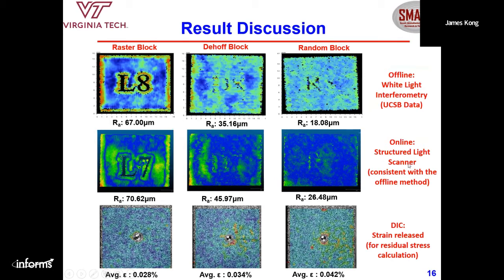With our structured light scanner, for each surface we only spend like 10 to 20 seconds. It's much, much faster. And the result in terms of surface finishing still has some errors. We're still in the process of improvement, but it's reasonable, and some of them are quite close. At the top, you see raster block, Dehoff block, and the random block. That means different patterns of scanning for the printing. For example, during the printing, the laser has different ways of scanning, so different patterns. The second row is captured by using our scanner. You see some of them quite close, some with a little bit larger error.